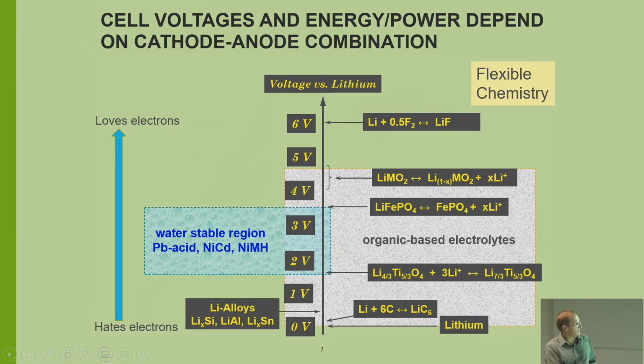Likewise, if you take water up to a higher voltage, it reacts as well, and you start having oxygen evolution. So here at the bottom, you have hydrogen evolution, and here you have oxygen evolution. People who work with lead-acid batteries, especially auto mechanics, know that every so often a lead-acid battery will blow up. If it's overcharging, you generate hydrogen at one electrode and oxygen at the other, and if you have a spark, they explode. I actually did that in high school once when I was welding on my dune buggy.